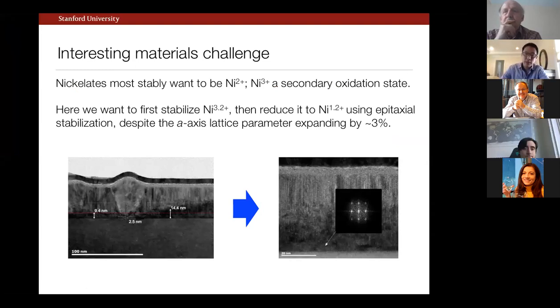Yeah, so we're doing that slowly. Let me just make sure I was clear. If we take the undoped case, neodymium nickel O2 or lanthanum nickel O2, there's already a fair amount of prior bulk work. What I mean to say is that the perovskite O3 versus the O2 phase requires an a-axis lattice expansion of about 3%. And so if we've grown and played with this in film form, we have this interesting dilemma.